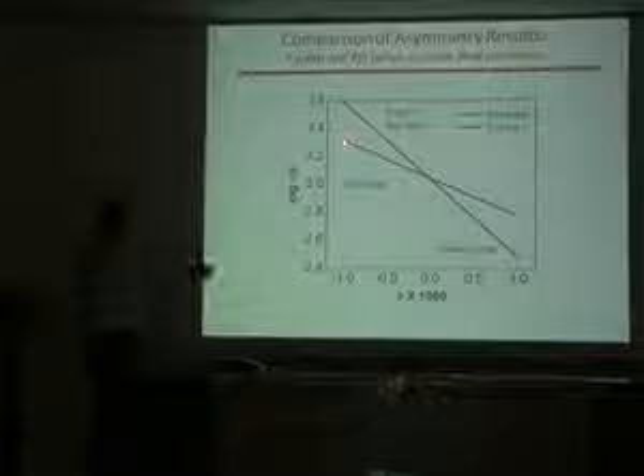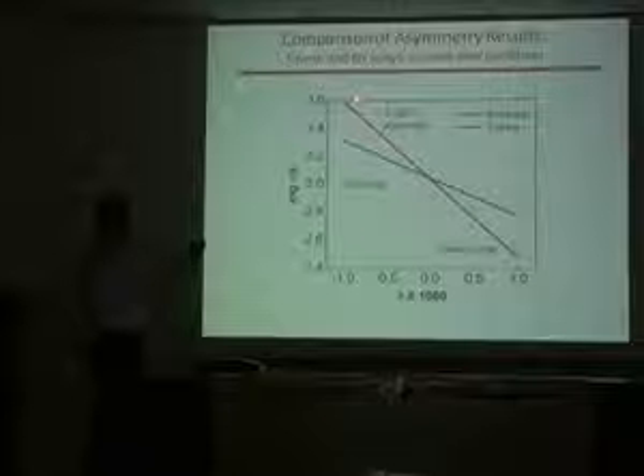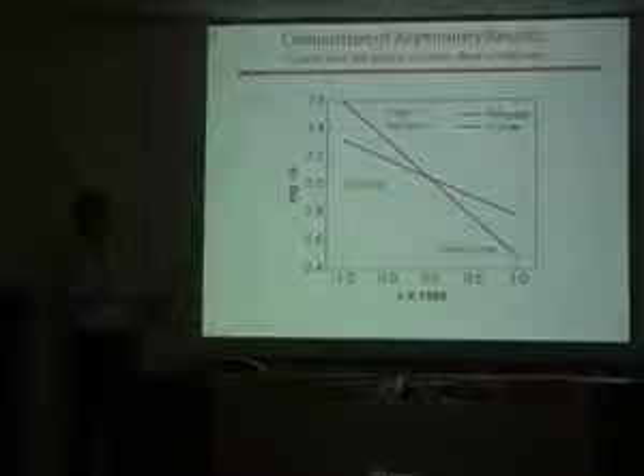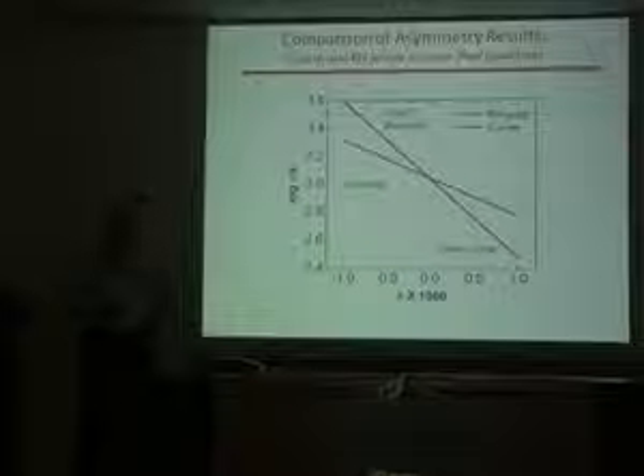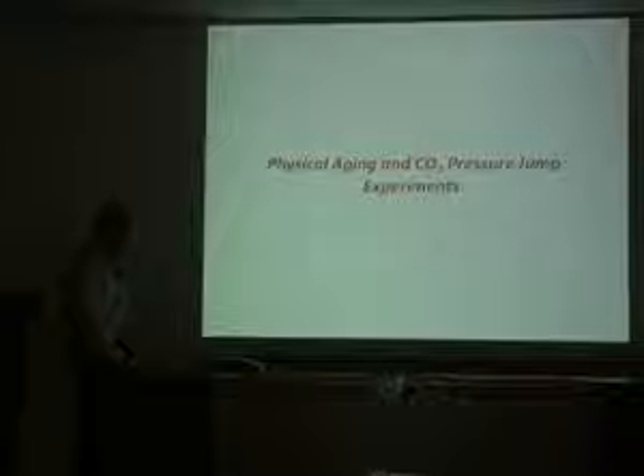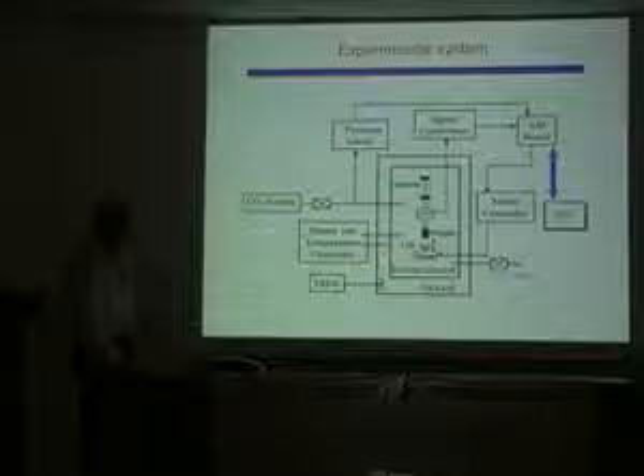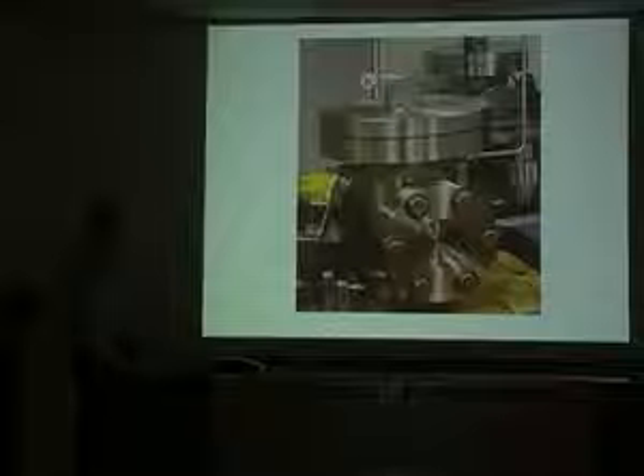But now, when we're on the other side, since these lines continue, now when I'm in a deficit of volume, it turns out my relative humidity experiment has a faster relaxation time than my temperature experiment, and that's why I have a lower asymmetry. Okay, so here they're slower, and here they're faster, so I have a lower asymmetry of approach. Okay, so we were also able to do this at carbon dioxide pressure. We just had to do what we had done before with a pressure vessel. So we do a lot of experiments.